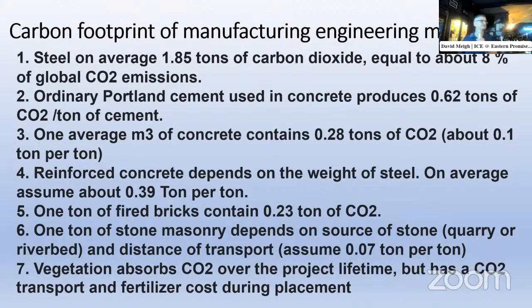And then ordinary Portland cement used in concrete produces 0.62 tons of carbon dioxide per ton, which is also a lot of carbon dioxide. So we need to look at a way of producing cement with less carbon dioxide. So on average, 1 cubic meter of concrete contains, or emits, 0.28 tons of CO2, about 0.1 ton per ton.